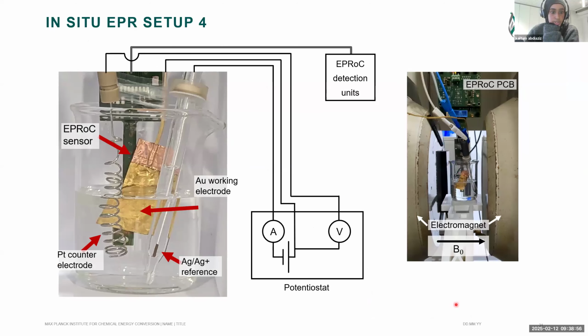So here is the setup that he used, where at the back here, you can see the PC board with the setup. So the EPROC sensor, and then a platinum coil for the counter electrode, a silver chloride reference electrode here, and then he uses this flattened gold sheet as the working electrode. So here he's using real, standard electrochemical electrodes. And then all of this is placed inside your magnet, so your electromagnet, and you can do the measurements.